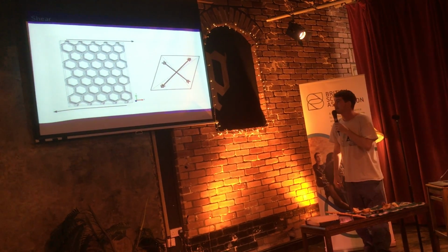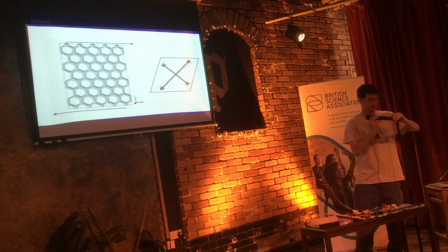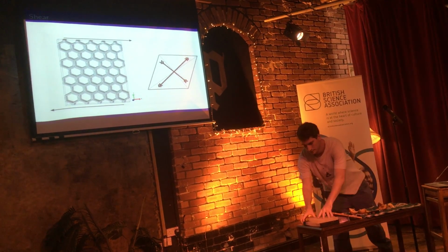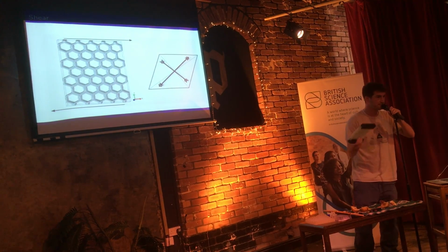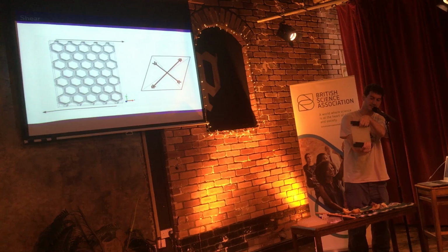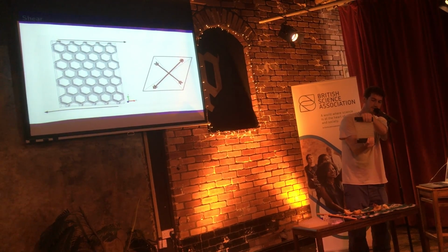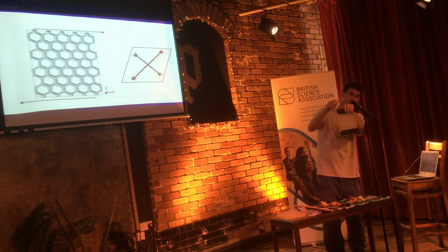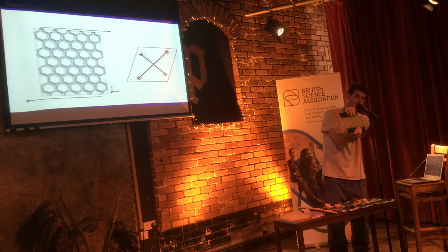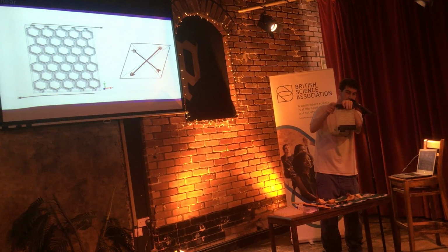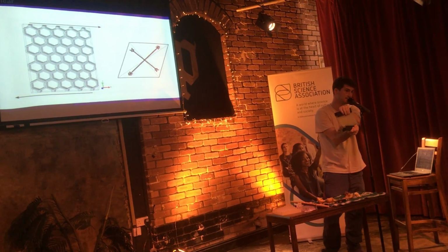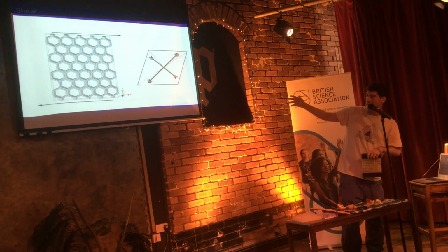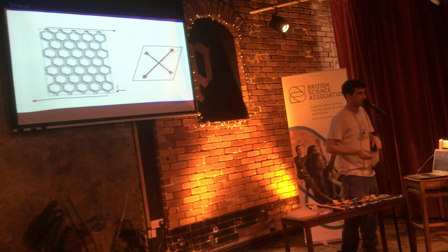Now, we also have shear. So for this material, I can either pull in tension, I can compress it, or to shear it, I'm pushing one side one way and one side the other way. And this corner and this corner are getting closer together, so they're in compression. In the same way, this corner and this corner are getting further apart, so they're in tension. So let's say these cells can separate. Where do you think the crack will occur in this material?